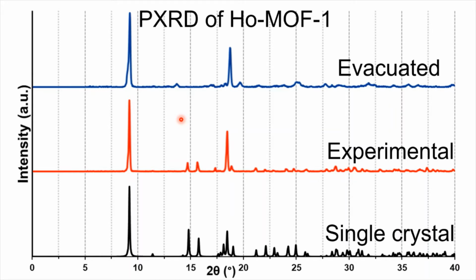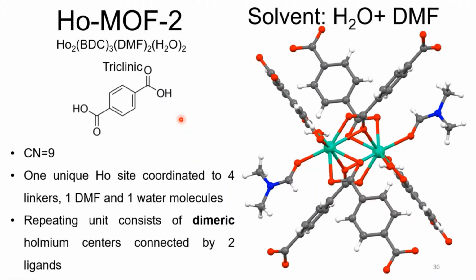As I showed you before, the structure doesn't look very porous. So when I ran gas adsorption measurements on this sample, it wasn't good. But now let's go into more synthesis conditions. So here we start changing some of these conditions. We have, for example, a different solvent, DMF. And what this did was change the coordination number around the Holmium centers, and it changes just how the linker behaves, how the repeating unit changes.